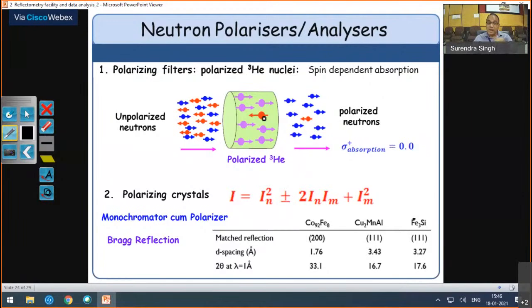Square. Okay, sorry, this whole thing is I square. The left side is I square equal to In square plus 2 In Im and Im square. Okay, so what happens for spin up? There are a few materials like Heusler alloy, copper 2 MnAl, and for not all planes, one plane which has a d spacing of 3.43 angstrom. Okay, so these planes, because this magnetic structure as well as the nuclear structure has the equal component, In equal to Im for this material, and for spin up and spin down this plus minus comes. So you can see from this, it is very straightforward. For spin up, the whole thing is plus, and for spin down this becomes 0.